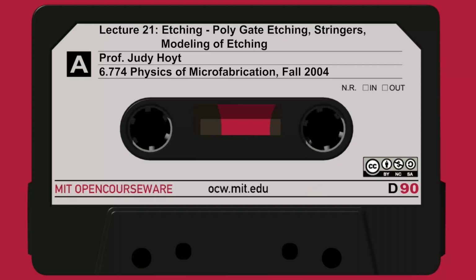Selectivity to the gate dielectric. Down here is a dielectric material, probably a high K, that's probably 1 to 2 nanometers thick. We need to stop immediately, as soon as we hit it, automatically, and not go through it, and not over etch too much. So this is a real issue, getting chemical selectivity at the same time as getting good sidewall profile. I just mentioned the fact that native oxide is often present on the polysilicon. We have to use a breakthrough etch as the initial step of etching, otherwise we'll have all kinds of grass problems.